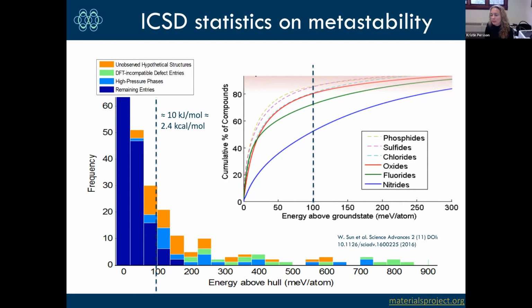So yes, energy above hull is a frequently used criterion for synthesizability, but it's not good enough. You can see that there are plenty of materials that can be made that are higher than about 100 meV per atom. And this is just for oxides. If you look at the bar graph, when you break out different classes of materials, you see that for oxides you hit about 80% of all synthesizable materials if you put your criterion at 100 meV above the ground state. But if you go to nitrides, you only catch 50%. So the class of nitrides clearly has a much higher degree of tolerance towards metastability than oxides do.